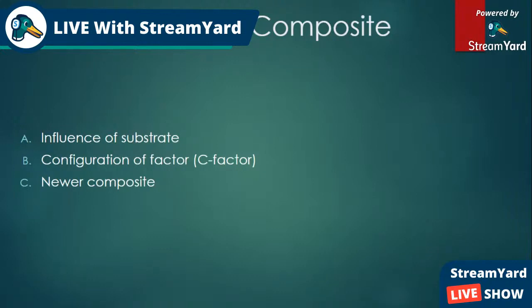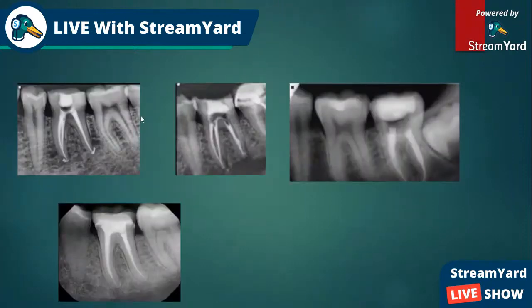So how many times have you seen it, like you have completed a root canal treatment, right? And you have filled the cavity with composite restoration, and after curing it, when you have done the x-rays, it comes out like this. As you can see, there is a blackish area between the root fillings and the composite filling. This black area is the result of composite polymerization shrinkage. You can see it here in this second picture. This can lead to micro leakage and ultimately to the failure of root canal treatment. It doesn't matter if it happens 2 years later or 10 years later, it will be considered a failure. So to minimize this,